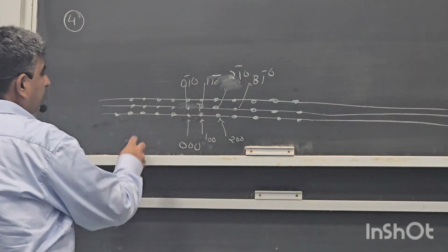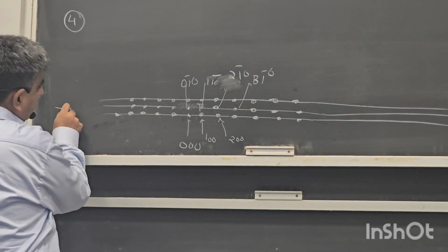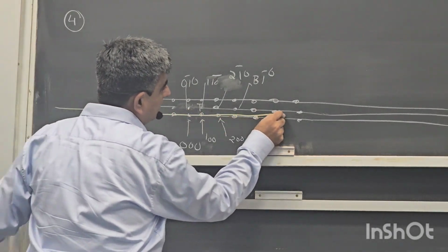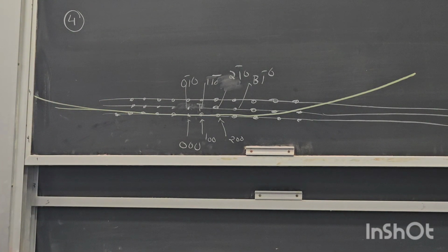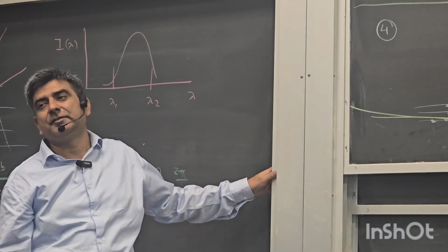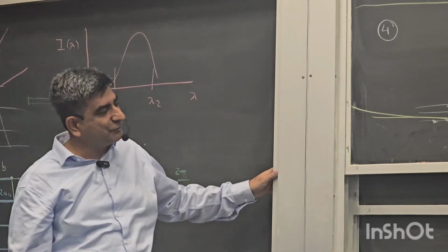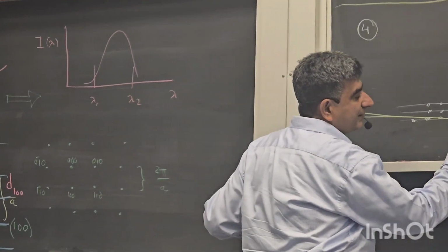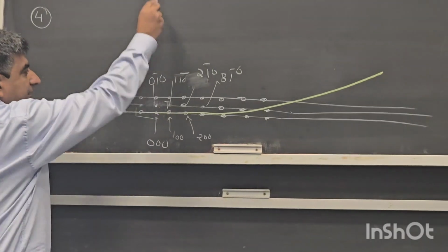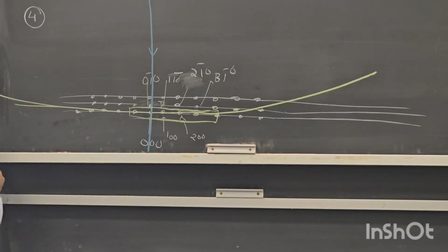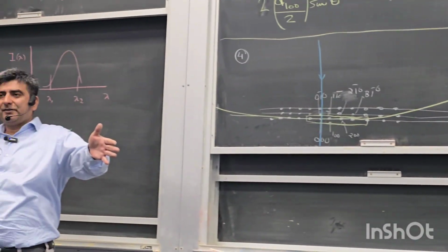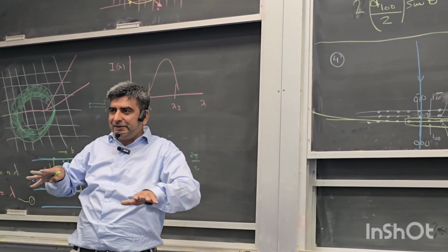If I have a really large Ewald sphere, with the curvature like this, because extremely energetic electrons have extremely short wavelength, then what's going to happen is that neighboring points near the exit circle, this is my exit circle for the electrons, these neighboring points in a row of the reciprocal lattice, all of them will lie roughly on this Ewald circle, because the Ewald circle turns very slowly.